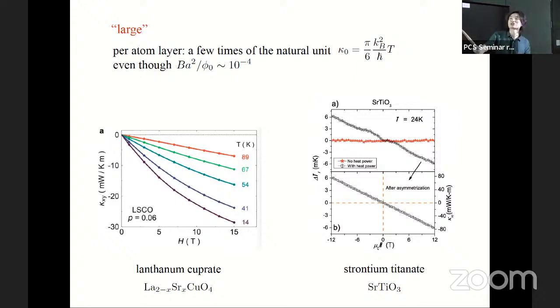And by large, first of all, it means in each layer of atoms, if you go to large enough magnetic fields, it can be a few times larger than this natural unit. However, it's very strange because it's linear in the magnetic field, and the magnetic field is very small. The magnetic flux per unit cell is 10 to the minus 4, even when the magnetic field is like 10 Tesla, in the natural unit of the lattice. So the magnetic field in the natural unit of the insulator is very small.